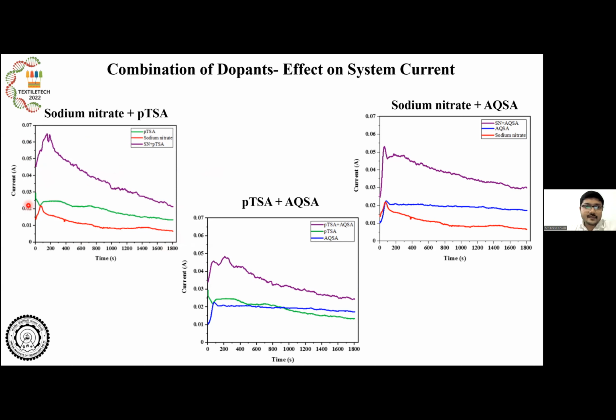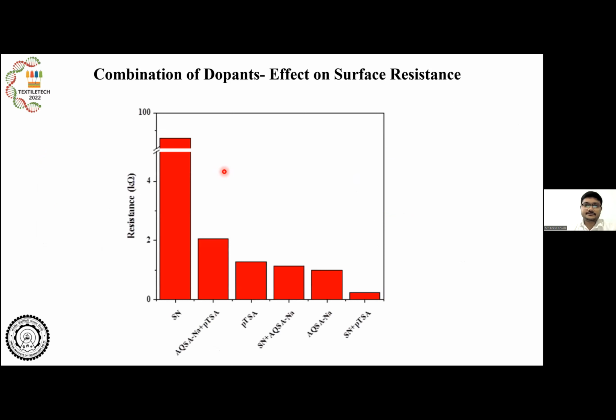These are the individual currents due to the individual compounds, and this is the current obtained when the polymerization was done using the sodium nitrate PTSA combination. The higher the current, the higher the energy available for polymerization, which leads to higher polymer deposition, which certainly results in higher conductivity of the polymer formed. So this graph confirms that the sodium nitrate PTSA combination is the best one, since the resistance is lowest with this combination.